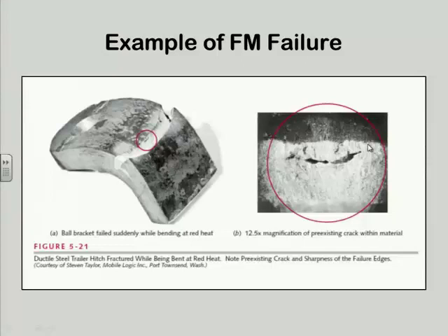This surface looks like a brittle failure. Does not look like a ductile failure. This is ductile 1020 steel. And it was red hot, which makes it even more ductile. It's out in the plastic zone. And it cracked instantly in a brittle-like failure. And when you handle it, it's sharp on the edges.